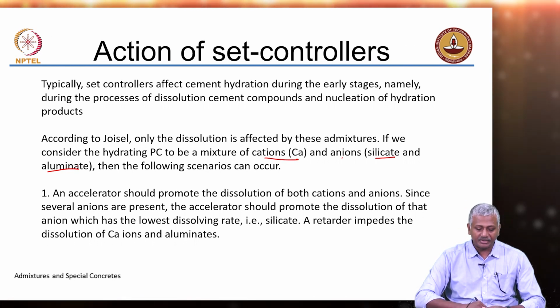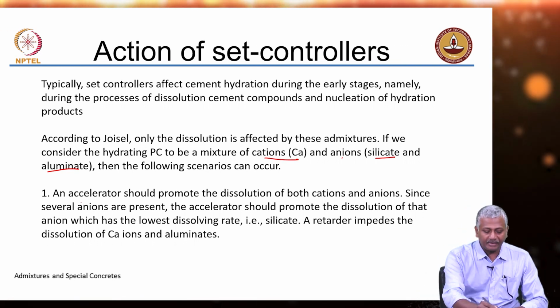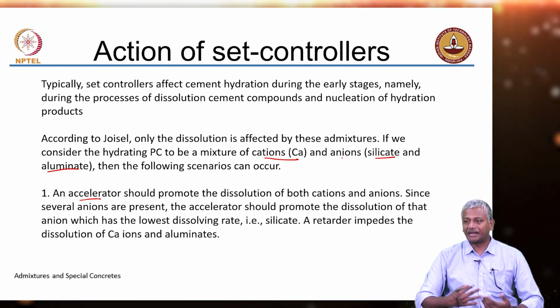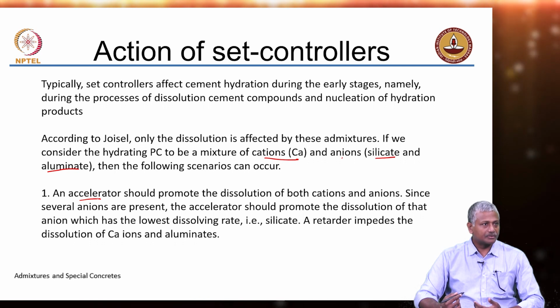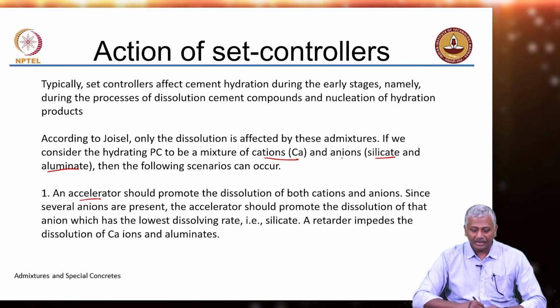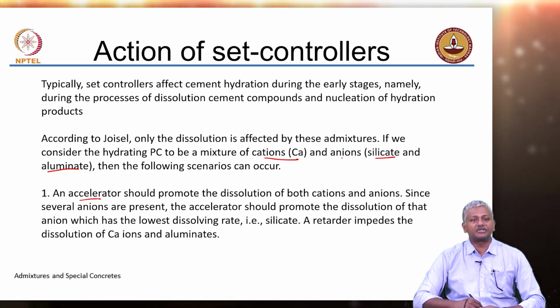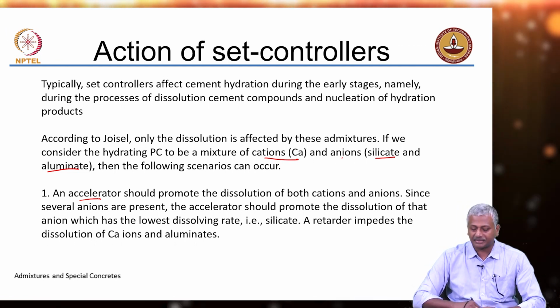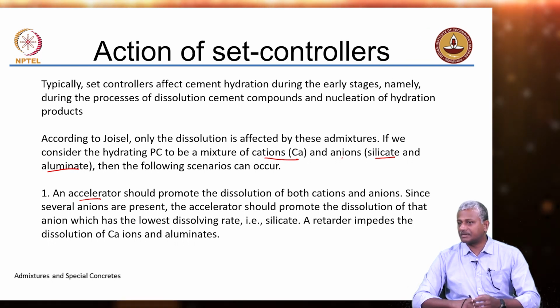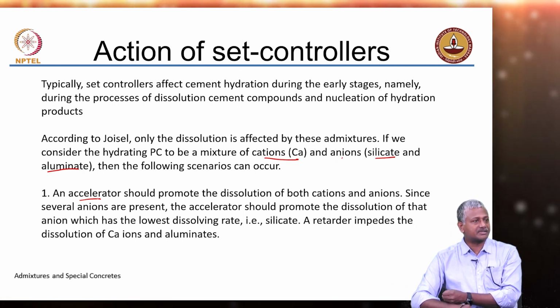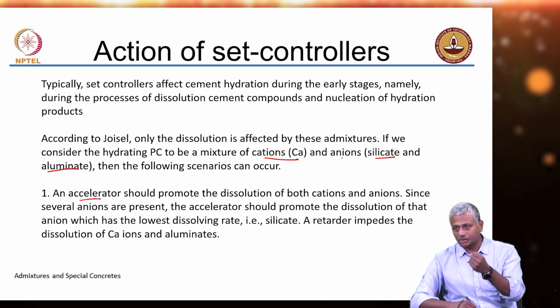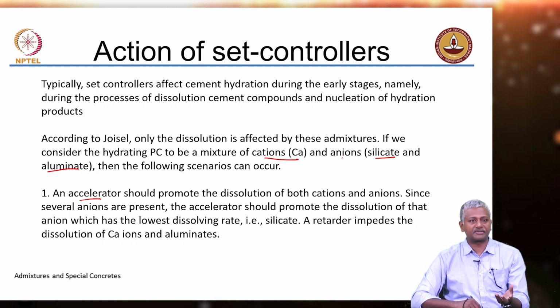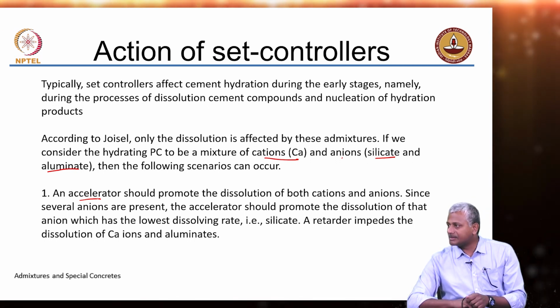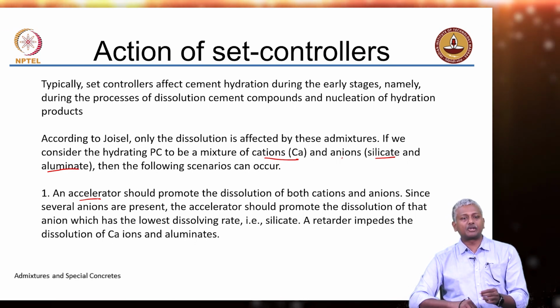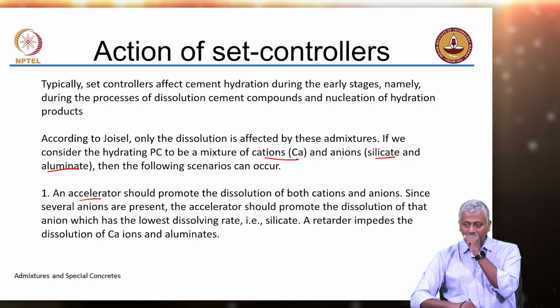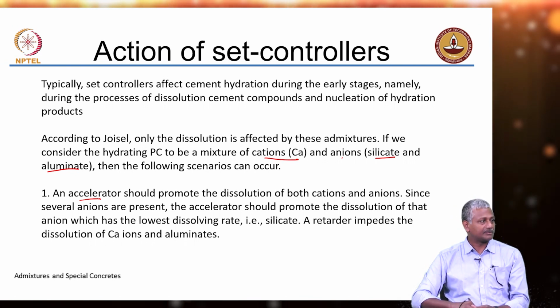So, the following combinations according to Josel can happen. One, an accelerator should promote the dissolution of both cations and anions. So, it should promote the dissolution of the cation, which is calcium, and it should promote the dissolution of the anion which has the slowest rate of dissolution, that is silicate, right, because aluminates, you know well that they react fast, silicates react slowly. So, the accelerator should affect the silicate. A retarder should be just the opposite, right. Retarder should impede the dissolution of calcium, it should also impede the dissolution of which anion, aluminate or silicate? Aluminate, because it is a faster reacting anion.